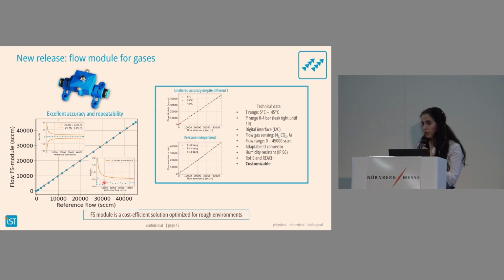What we also tested was to do the same test at different conditions, so different rough conditions, different temperatures. The flow output is not altered. We have different temperatures here for the whole flow range. And we also did a similar test for different pressures. And also here there is no change or worse accuracy response. So we have, all in all, a very robust solution that is cost optimized.